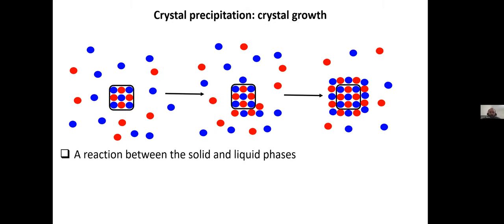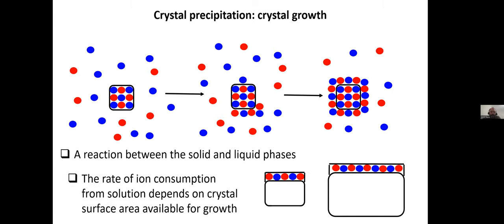The second process when we talk about precipitation is crystal growth. Once I have crystals in a system, it's thermodynamically favorable to grow them rather than to form new crystals. So this is already a reaction between the formed solids and the aqueous phase. One thing to remember for the rest of the talk is that if I measure the chemistry of the solution during the time that a new surface layer of the crystal grows, a larger crystal will take more ions. So if I measure the chemistry, I'll see a larger change if I have a larger surface area of crystals. And this is also something I'll mention during the talk a few times.